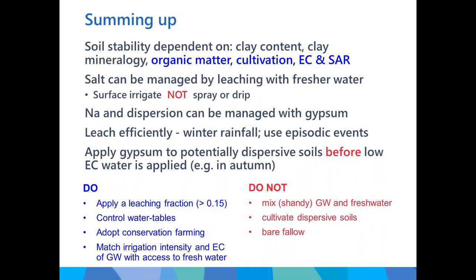A couple of big do nots. Don't shandy your groundwater with your fresh water. There are some technical reasons for that, but the main reason is that you can reduce your conductivity by half, but you'll only reduce your sodium, your SAR, by 0.7. So you don't reduce your sodium in the same proportion as you reduce your total salt load. So you get fresher water, but it's got a higher proportion of sodium in it. That's just the way the ratios work. So by shandying your water, you can actually get a poorer quality water applied.